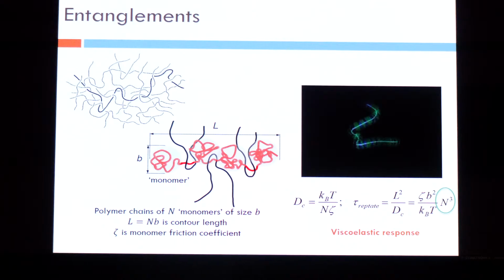So if I can please play that video again. You see there one of these molecules, the white thread that I have shown in this molecule. Around it are these colored entanglements. And now what happens is these molecules, because of the entanglements, can only move in and out of that tube. It's almost like a reptilian motion. It's like a snake or a worm that moves in and out of that tube. It's only when the molecule exits the tube that it can relax, because it has escaped the entanglements.